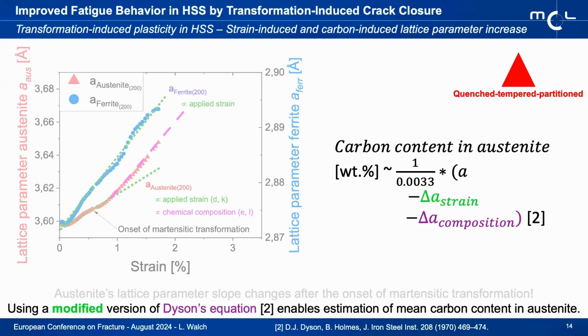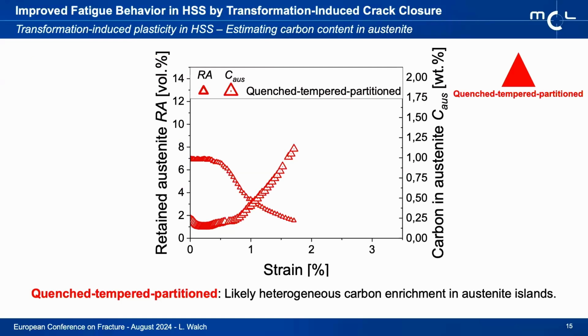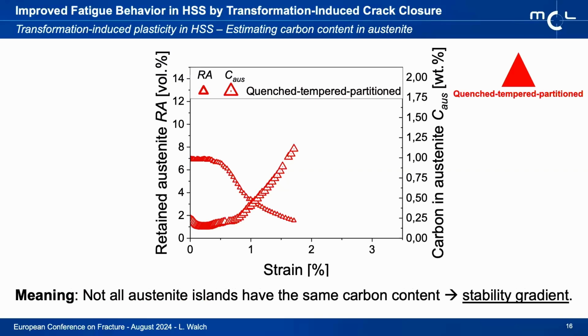And by slightly modifying the well-known Dyson equation, we estimated the carbon content in the austenite phase. Please keep in mind that that's just a general estimation. So the trend is probably correct, but anything more than that requires further evidence. Still, what we can see is that the final austenite that's left at the moment of specimen fracture seems to have a higher carbon content than the one that is transformed here first. This indicates that there's a difference or heterogeneity in the stability of the retained austenite islands in our material state, which is to keep in mind later for the fatigue results.